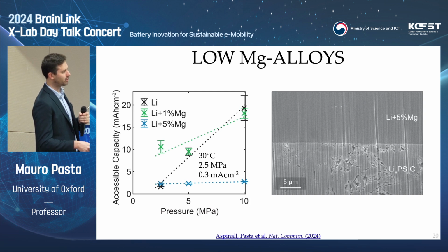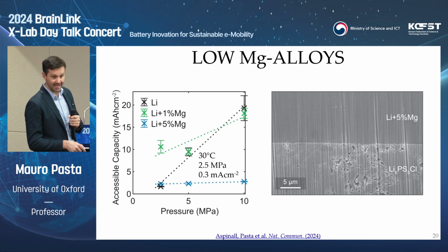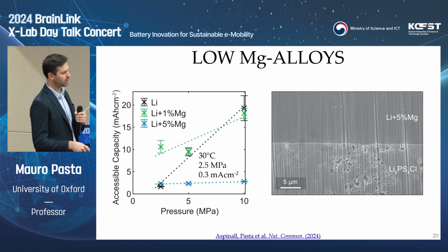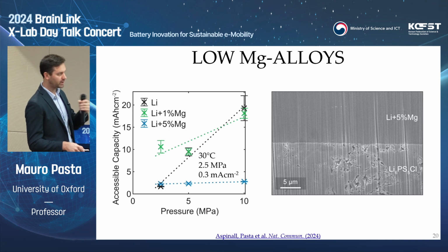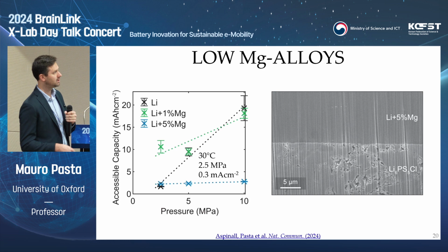So the whole concept that we would explore is to go even below 5%. So 1% magnesium is enough to help retain contact, while at the same time being less pressure dependent and accessing quite a bit of capacity even at low pressures. Yes, this helps with contact retention and voiding. We're still working right now on trying to increase transport within lithium itself by looking at secondary phases, secondary components, and it's something that hopefully we'll publish soon.